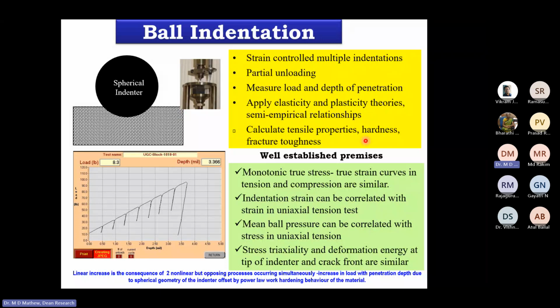So once you process the data, what do you get? You will get monotonic true stress, true strain curves. And the assumption is, in this case, that the true stress, true strain curve, which you have generated under compression mode, compression loading, is similar to the true stress, true strain curves in tension. Another assumption in this processing of the data is that the indentation strain can be correlated with the strain in a uniaxial tensile test.